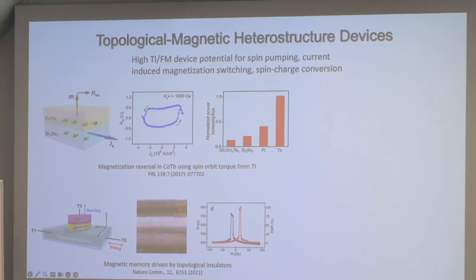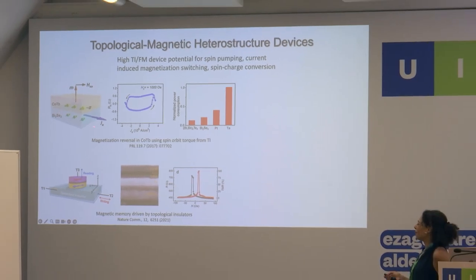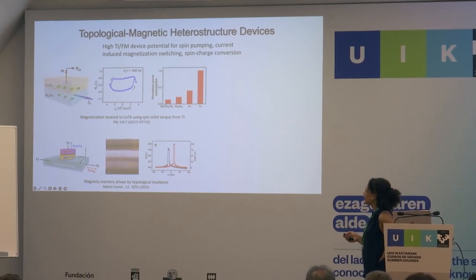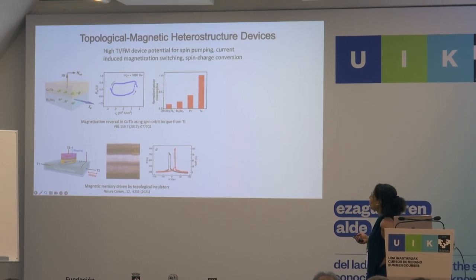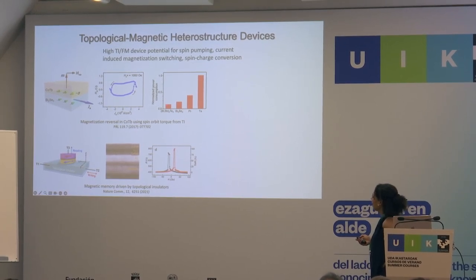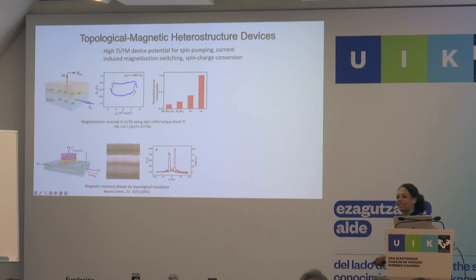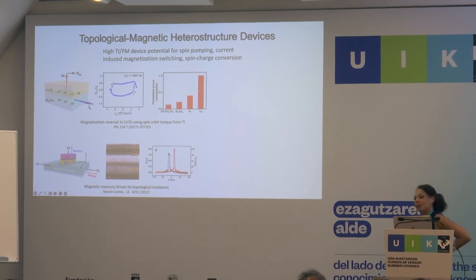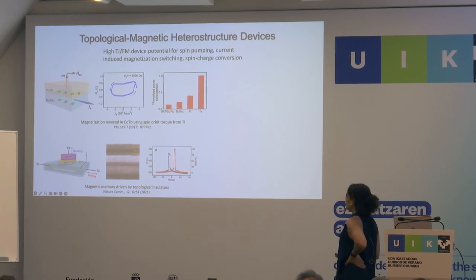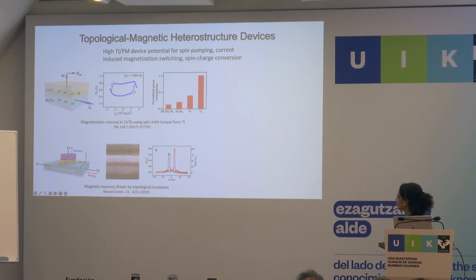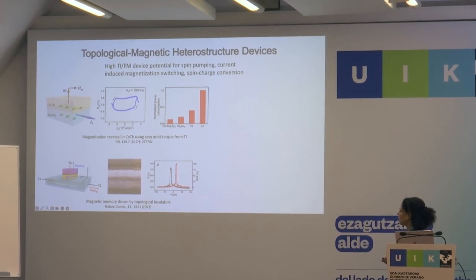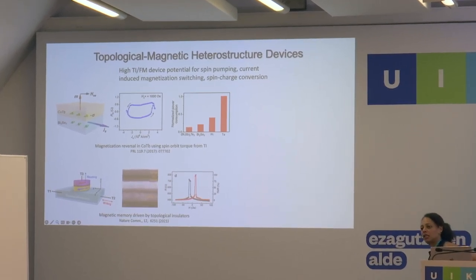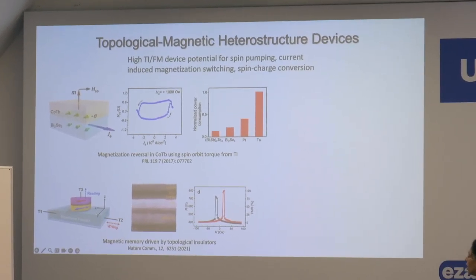You can reverse the magnetization in cobalt terbium in a multilayer of bismuth selenide and cobalt terbium, and you can see that the amount of power consumed in doing this using bismuth selenide is much lower than what you use using either platinum or tantalum, which is a pretty remarkable effect because platinum is what's used all the time for spin torque transfer systems. And more recently, there's been an experiment showing that if you use a topological insulator with a magnetic multilayer in the same configuration that you'd use for MRAM, you can get a switching effect which is comparable to what you'd see in MRAM-type devices at even lower power.